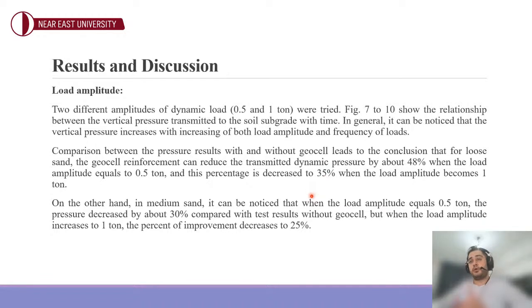However, if we are using medium sand, which has a relative density of 60%, this reduction in the pressure transmission will reach 30% if we are using 0.5 ton. However, if we are using 1 ton, the improvement or the reduction of the pressure transmission reached 25%.